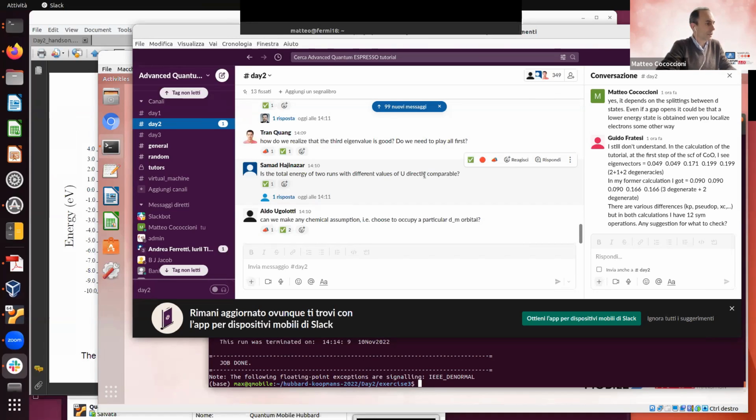I won't do it in this hands-on because there is not enough time. To break the symmetry, sometimes you just need to break spin symmetry, and that's okay if you already have an antiferromagnetic compound. Other times it is required, like for iron oxide I was mentioning this morning, that you construct a supercell, then it's more complicated, and of course the cost of your calculation increases.